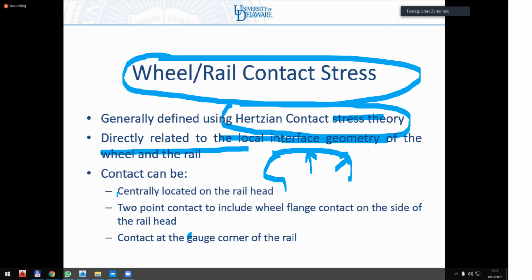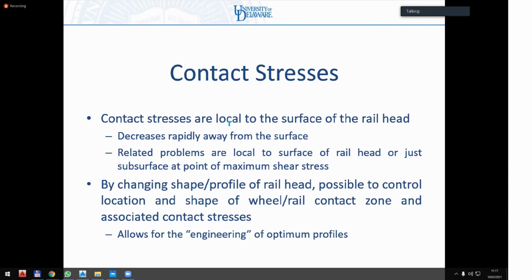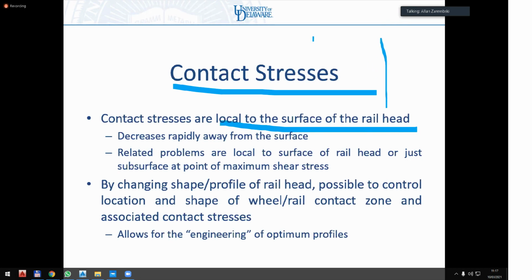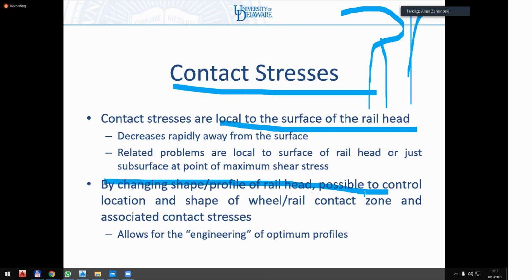And so contact can be central on the rail head. It can be two-point contact, which includes wheel flange contact on the side of the rail head, and then contact in the gauge corner of the rail, all of which we've talked about. So there's my central contact. This is actually a 1-point contact where I'm contacting at the flange root gauge corner of the rail, and then the field contact we showed. Okay, so contact stresses are local to the surface of the rail. If this is my rail and I plot my contact stresses, they fall off very rapidly. And they're actually related, as I said, to the shape and profile of the rail.